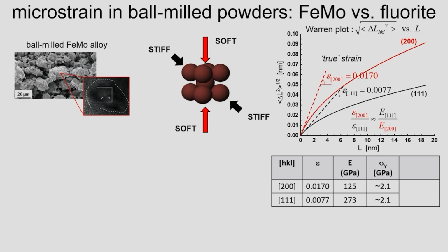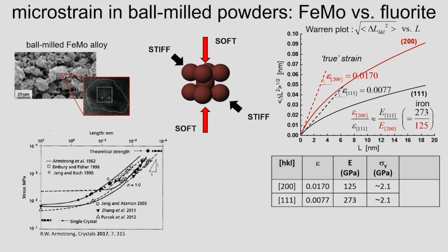And think of it, it is much higher than in normal bulk large crystals, because when the size becomes very small, at some point you cannot break the crystal using dislocations because it's too small. So the materials become kind of intrinsically stronger. Much of the fuss about nanocrystals is also because of this. Studies like this one show more or less the trend of the maximum stress depending on the size. And if you look at the value for 10 nanometers, which is here, you see that it's in the order of 2 to 3 gigapascal, which is more or less the value we find.